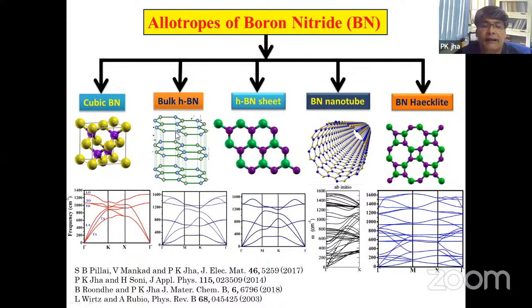When it goes to bulk hexagonal boron nitride, because that is a layered structure, as you can see from here, you have the out of plane acoustic mode. Then it is the 2-dimensional boron nitride sheet, and you can see here that the phonon dispersion curve has a nature, of course, similar to the bulk hexagonal boron nitride, but with a different nature. This is for the boron nitride nanotube. You can see the dispersion relation. This is for the boron nitride Haecklite, a different structure. And you can see here, because the unit cell contains more number of boron and nitrogen, therefore it has a large number of phonon modes, right?